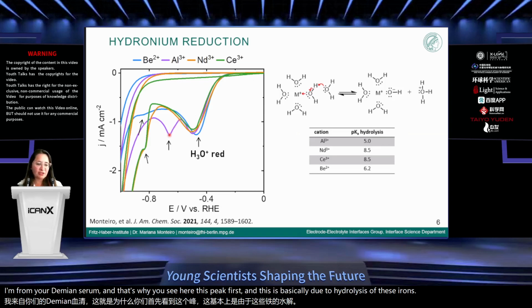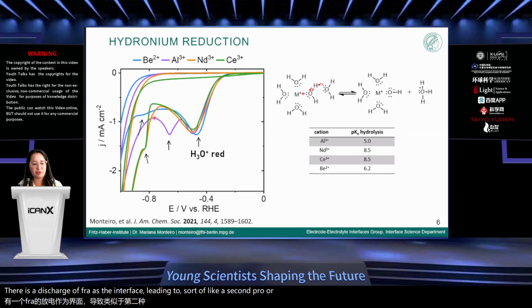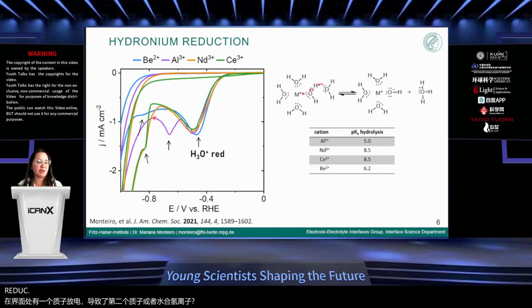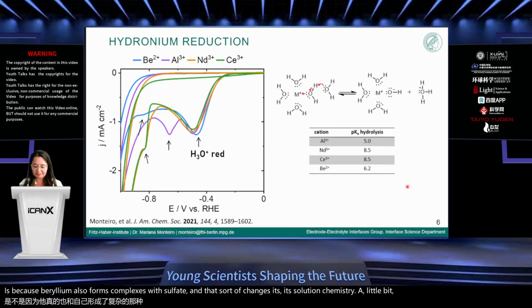There is a discharge of protons at the interface, leading to a second proton or hydronium reduction regime. The trend is just not followed by beryllium, and the reason is that beryllium also forms complexes with sulfate, which changes its solution chemistry a little bit.